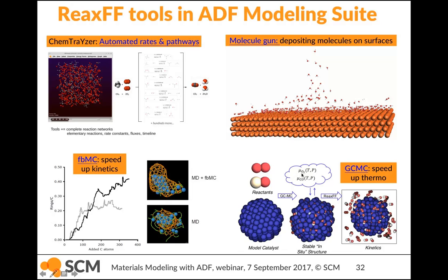Then you want to get the actual catalytic structure of that particle under reaction conditions, under different oxygen partial pressures and temperature conditions. So at low oxygen pressure, that's going to be a surface oxide, whereas at higher oxygen pressure, that's going to be more like a palladium oxide.